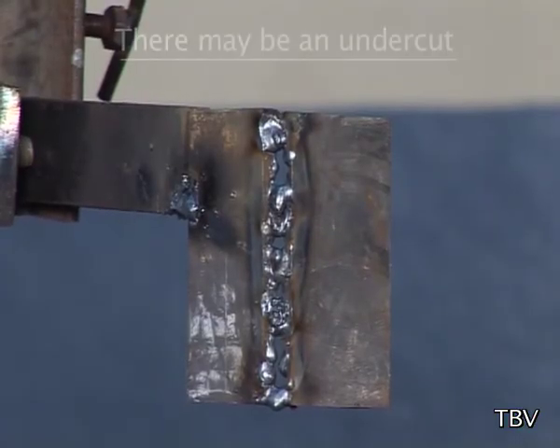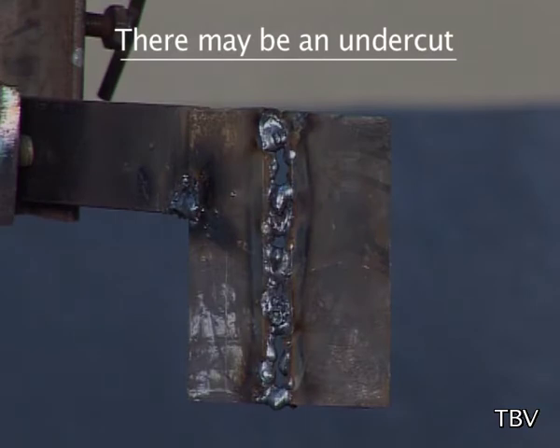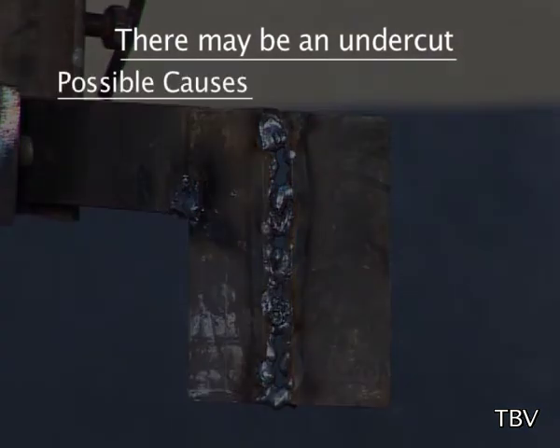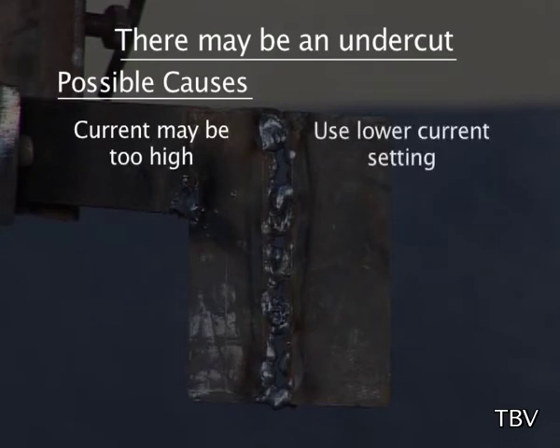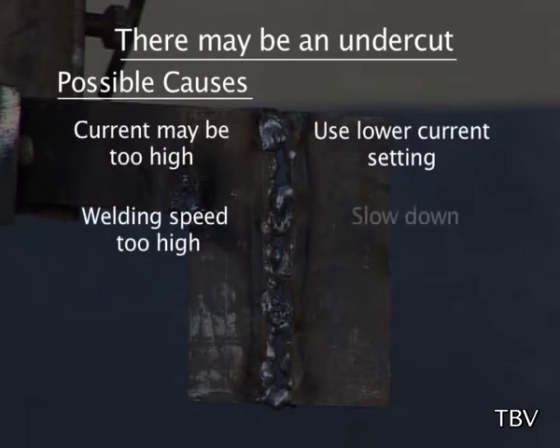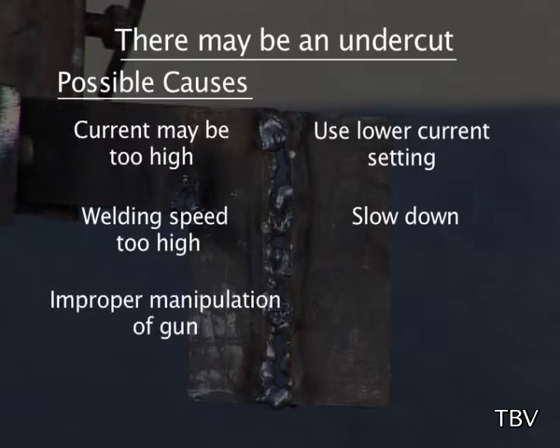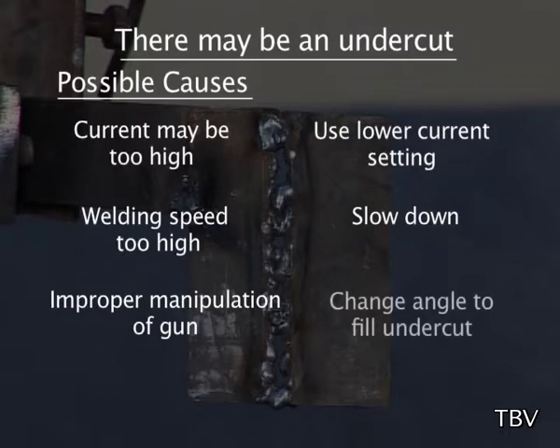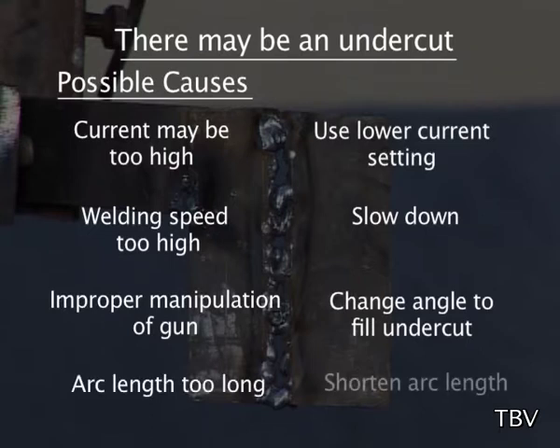Defect: there may be an undercut. Possible cause: current may be too high. Remedy: use lower current setting. Possible cause: welding speed too high. Remedy: slow down. Improper manipulation of gun. Remedy: change angle to fill undercut. Arc length too long. Remedy: shorten arc length.